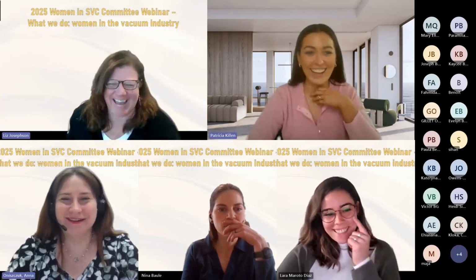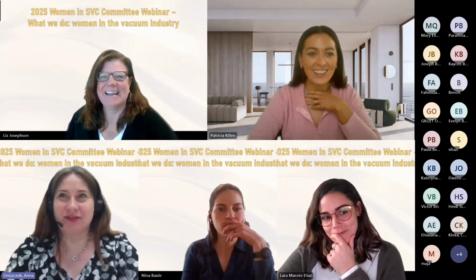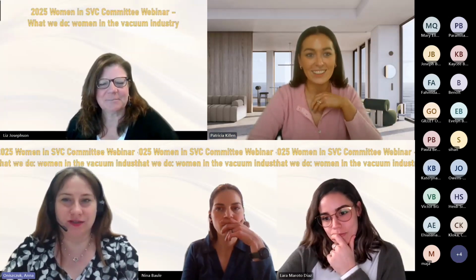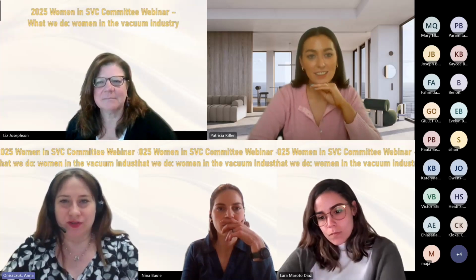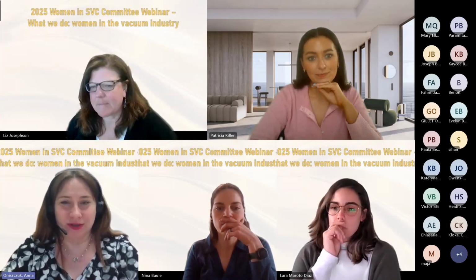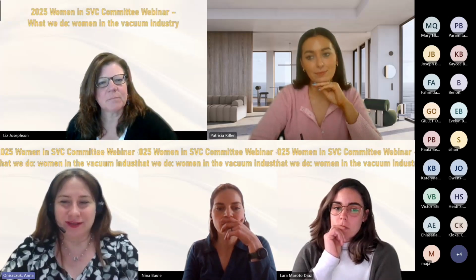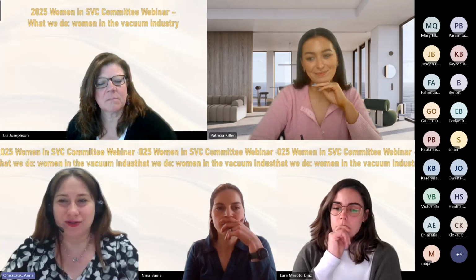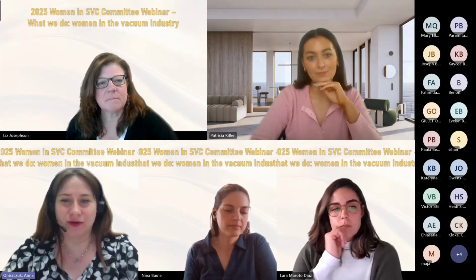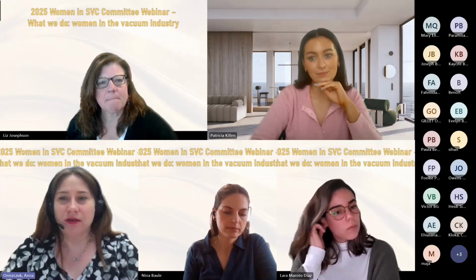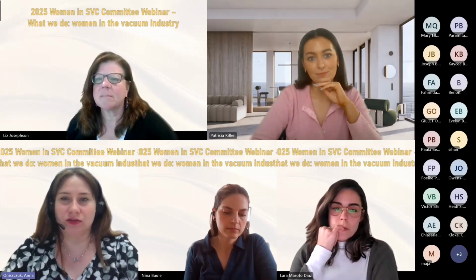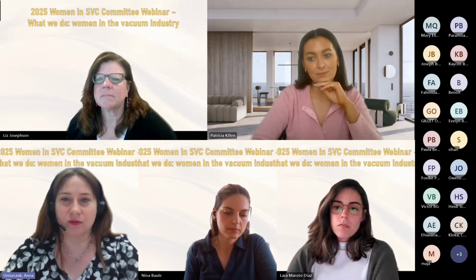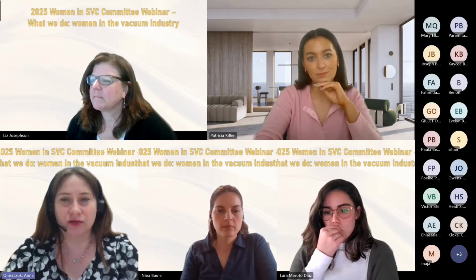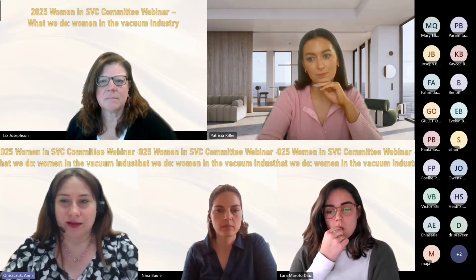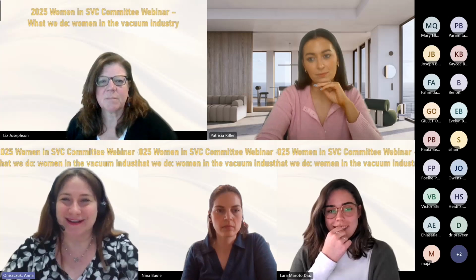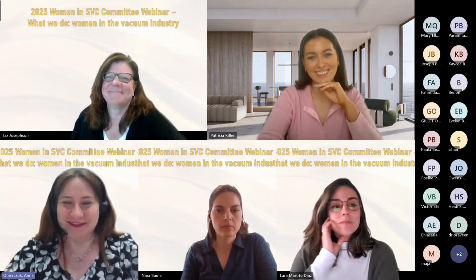Oh, Anna, yeah. Okay, so I can answer some of the questions. So definitely when you're depositing titanium nitride, it's a relatively simple deposition. However, you always need to think about the stoichiometry of the coating. So in order to have this nice shiny golden color, you need to remember that it's a reactive process, so you need to control the gas consumption very well. And in order to have a good coating, usually you need to have very good energy. So quite often this coating is deposited at a higher temperature. And if you cannot get a very high temperature, you can always use HiPIMS to enhance the energy. So that's also a very good way.